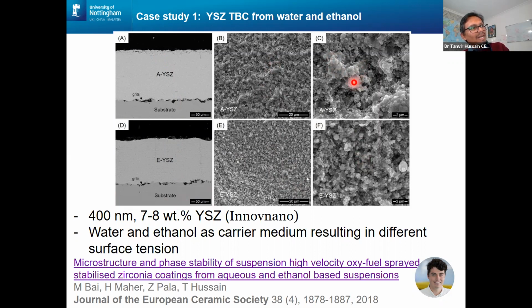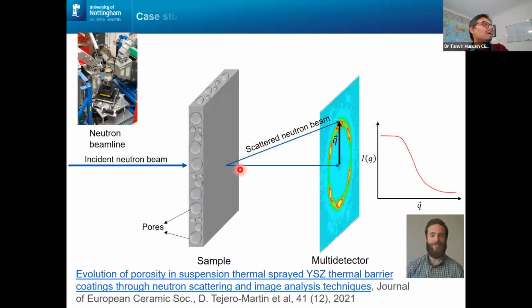And you can see the splat size, which is the building block of coatings, are different. And that's down to the surface tension. When you're injecting water into an HVAF torch, you're essentially cooling it down, and because of the surface tension, the particle droplet tends to be bigger. With ethanol, you're adding more fuel, so you are adding more heat, but because of the surface tension of the droplets, they tend to be smaller. So it produces different types of microstructure in the coating, and in this particular paper we were exploring the effect of suspension medium.